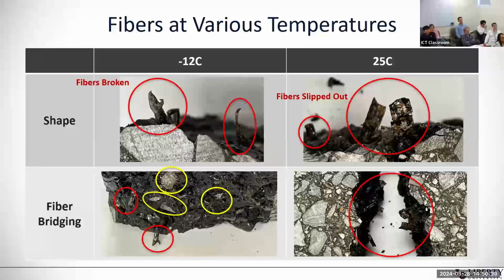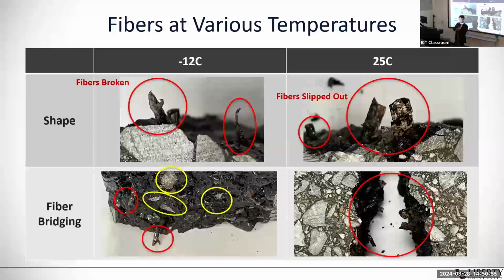Yeah, that's a good question. What the student is doing this week and next week is trying to see the friction between the binder and the fiber at different temperatures. We couldn't find the specification for that. What we are going to do is have those tubes, fill the binder in them, and then put the fibers in. Then we put them at different temperatures and pull them to see the friction between the binder and the fibers. That will explain the governing factor that makes the fiber break at different temperatures, or whether the type of binder or the type of fiber also affects it.